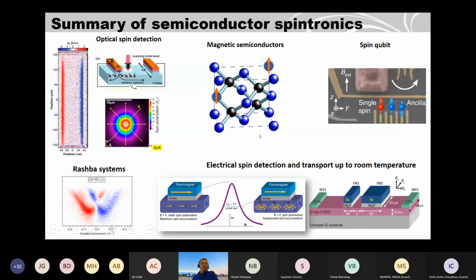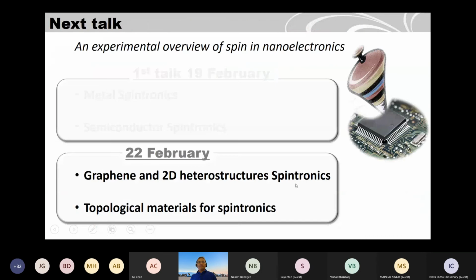To summarize my talk for this part, what I have shown you is that one can optically create spin polarization in a semiconductor and detect it also by optical methods. The spin Hall effect was also first observed in gallium arsenide semiconductors, though now it is more used in metallic systems for making more active spintronic devices. Magnetic semiconductors are tunable, but they have a low Curie temperature. Spin qubits are also interesting. And we can see how we can do all electrical spin injection, detection and transport up to room temperature in semiconductors.